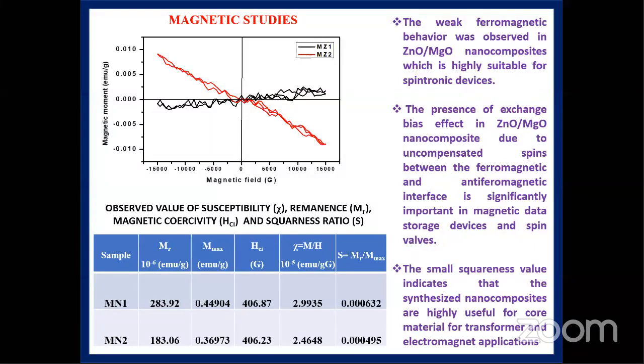You can see we calculated magnetic parameters like susceptibility, remanence, magnetic coercivity, and squareness ratio. We tabulated them here, the first ratio of the sample. The small squareness value indicates that the synthesized nanocomposites are highly useful as core material for transformers and electromagnet applications.